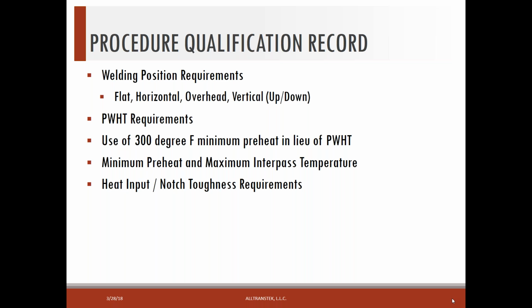And then, of course, with notch toughness requirements, we have to measure the heat input when we qualify the welding procedure, and then we can't exceed that heat input. The formula there would be amps times volts times 60 divided by your travel speed, and that's the formula that would be used to calculate heat input.